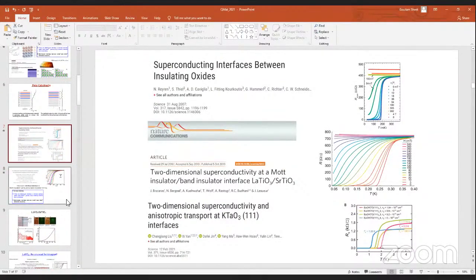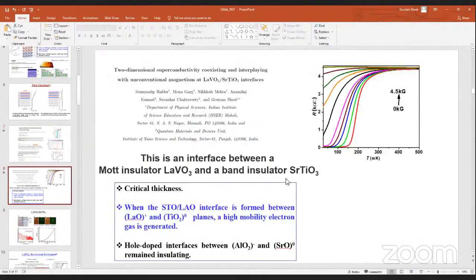So we do not care about the origin of the superconductivity here. In this case, we are using the superconducting part of the interface as a sensor of the magnetic states that we are writing, reading, and erasing. Even in the case of LAO STO, the superconductivity is actually on the STO side, but this is still effectively a 2-dimensional superconductor.